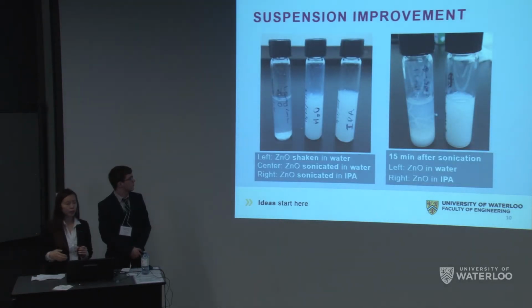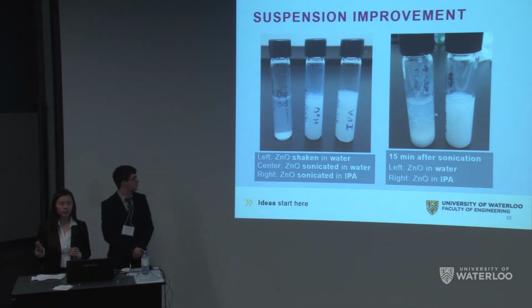So just from doing this multiple times, it took us about 10 minutes to do this coating step. So therefore, it was mandatory to obtain a suspension that will essentially remain suspended for the entire duration of the coating step. And we figured out that ZnO, sonicated, in IPA works the best.